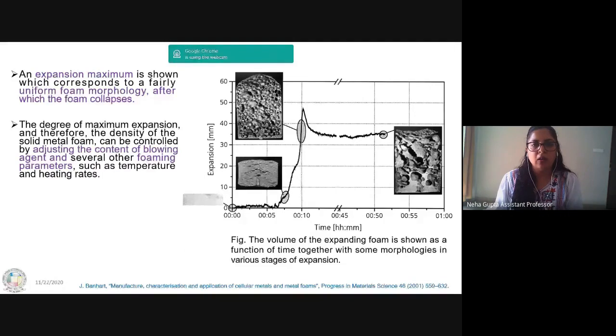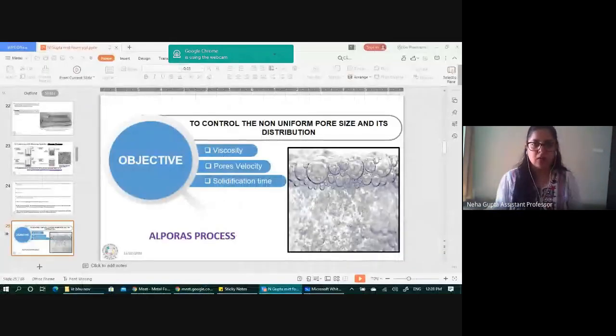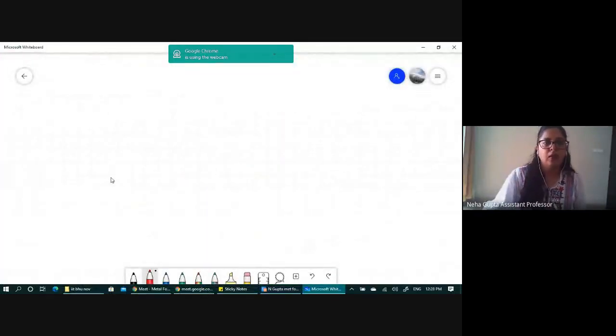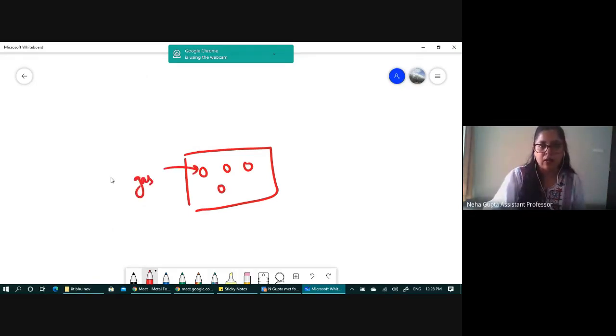So here you can see at the time of 0.5 minutes, this was your initial expansion, and slowly at this point, at an expansion of around 40 mm, you are getting this kind of structure. And here somewhere you are getting a collapsed pore structure. Now what happens when you are developing any kind of pores? So this is the volume. In this volume, you have some pores, and the property of a pore is that you have gas in it. The property of gas is that gas always expands with time. Okay, so as you increase the time, this gas bubble will expand.